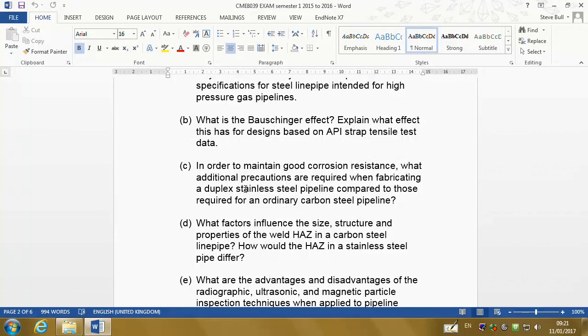Now, we say the size, structure and properties. The size of the heat affected zone is the difficult one here, because I didn't specifically talk about the size of the structure. The heat affected zone in stainless steels is usually smaller than the heat affected zone in carbon steels, because the thermal conductivity of stainless steel is lower than in carbon steel. So the heat cannot escape from the weld quite so quickly. So that bit you may not know.